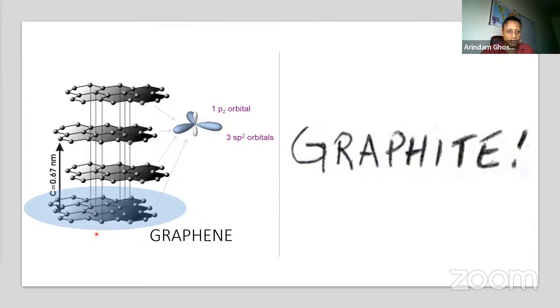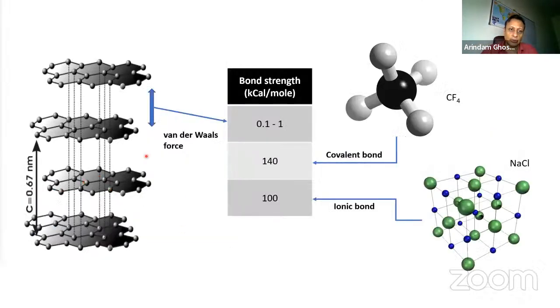What happens is the interaction between the 2 layers is extremely weak compared to a 3-dimensional solid, which is covalently bonded or ionically bonded. For example, these 2 layers are usually bound with a very weak force called a van der Waals force. And if you compare the force between 2 successive layers in graphene, you'll see that it is about 1,000 times lower than usual covalent bonding or ionic bonding. For example, simple salt, the sodium chloride that we take in our food, the kind of interatomic strength or force is nearly 1,000 times that of graphene.